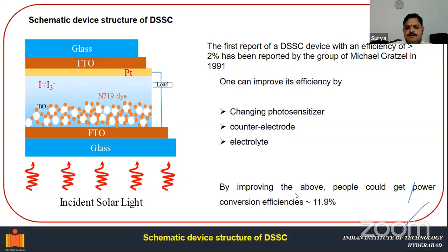By improving the above, by changing the photosensitizer, the counter electrode, and the electrolyte, people have been able to get power conversion efficiencies of the order of 11.9%, from 2% to 11.9%. It's a huge improvement, and still a lot of research is going on in these dye sensitized solar cells.